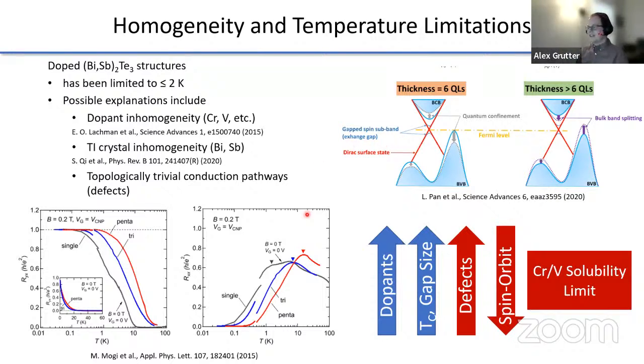So one of the things that people have suggested to improve the uniformity in these systems is we'll just increase the number of dopants until it's quite uniform. And this should increase your Curie temperature and also your gap size and uniformity. But on the other hand, it's a double-edged sword, right? You also are increasing the number of defect states, which can then give you more trivial conduction pathways. You're weakening the spin orbit coupling that actually gives you your band inversion in the first place. And you also will eventually reach the solubility limit of your dopants. And so at that point, you're just sort of stuck. You can't go any further. So there's a lot of challenges.